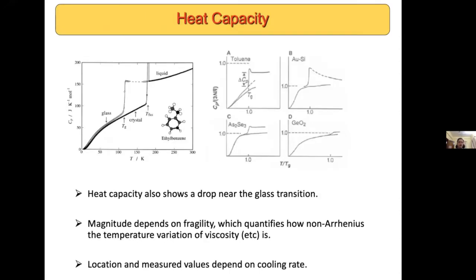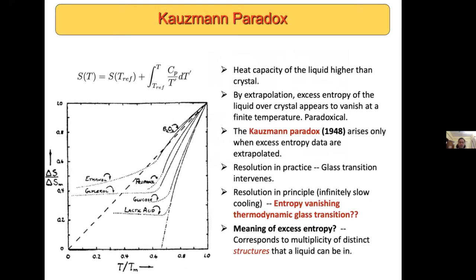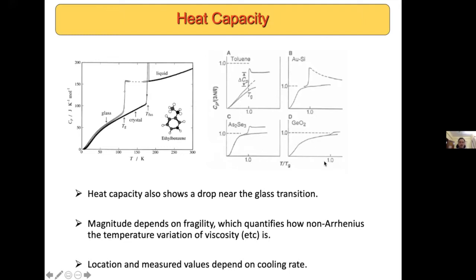Okay, so if one looks at other thermodynamic properties, such as the heat capacity, this shows near the glass transition a sudden jump. How sharp it is depends on details and depends also on the kind of glass former one is looking at. But invariably, the heat capacity jumps down rather sharply around the glass transition temperature. As also shown in these panels, the heat capacity not only jumps down, but is invariably higher in the case of a glass-forming liquid than the corresponding crystal when such a comparison can be made. And this is certainly something that can be done for several low molecular weight glass formers.